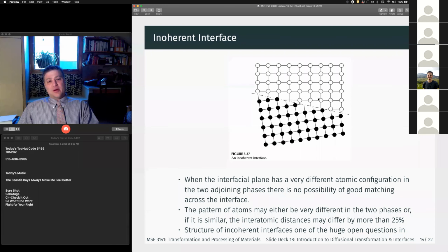But anyway, we no longer have a lattice correspondence, right? And you can imagine now we have essentially all of these dangling bonds, right? None of the atoms at this interface are in their preferred state at all, right? We have a very high energy situation with an incoherent interface, right? But in reality, this is what we get most of the time, right? If you have interatomic distances that vary by more than 15, 20, 25%, there's no way that you can maintain any kind of regularity of the interface, and we end up with a fully incoherent interface, right?